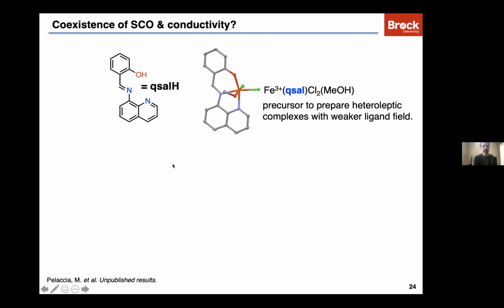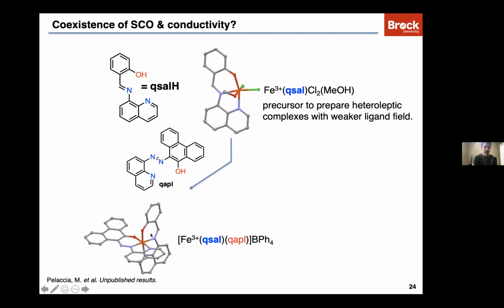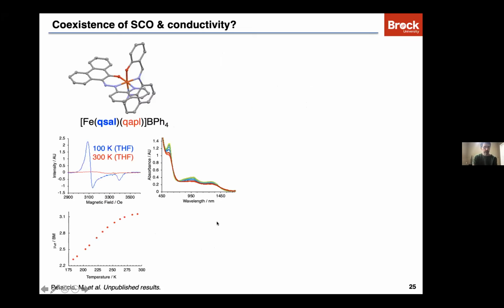So what we've been attempting to do is make heteroleptic complexes where we use this Schiff base ligand, quinolinyl, or qsal, and iron qsal complexes are well known. And we can make this precursor complex that has one qsal, one iron, and two chlorides, and then make heteroleptic systems with our aryl azo ligand. So if we react this precursor with QAPL, we can make the heteroleptic complex as a tetraphenylborate salt, one qsal, one QAPL. And we've made several derivatives of this. We've used halogenated qsals and so on.